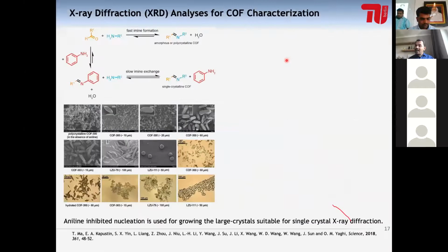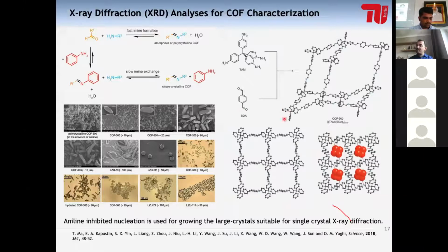And someone might ask, is it possible to synthesize single crystalline material like MOFs? Yes. In three-dimensional material, it has recently been shown that these materials can be synthesized as single crystals, and using single crystal XRD analysis, you can even characterize them very well with all the precise atomic positions. So now I will just show you that, as in metal organic frameworks, this tetraamine linker can start coordinating with different dialdehyde molecules.